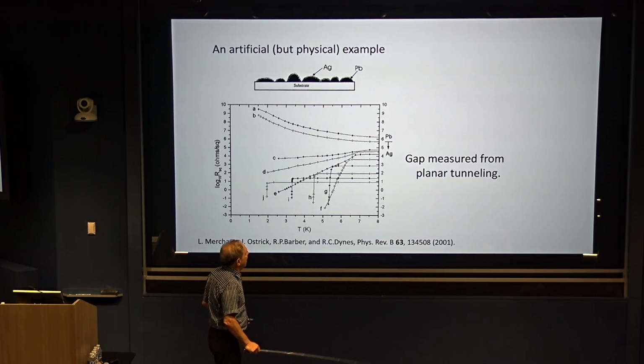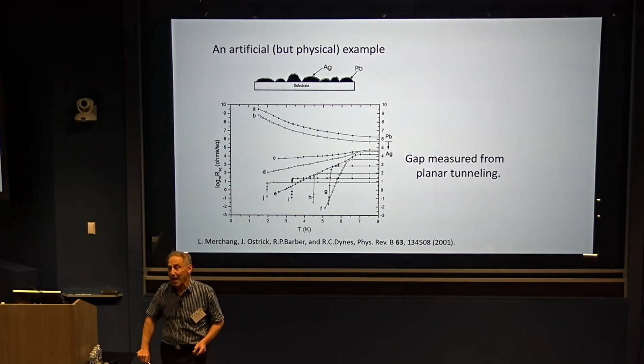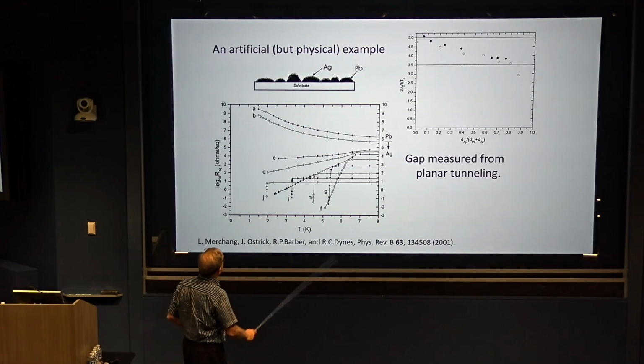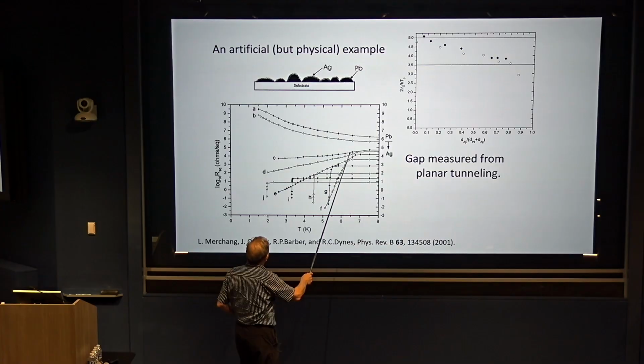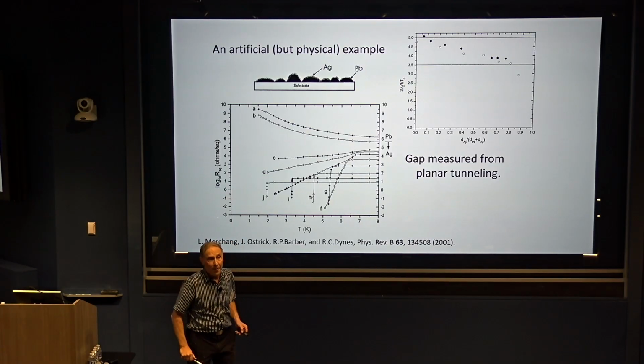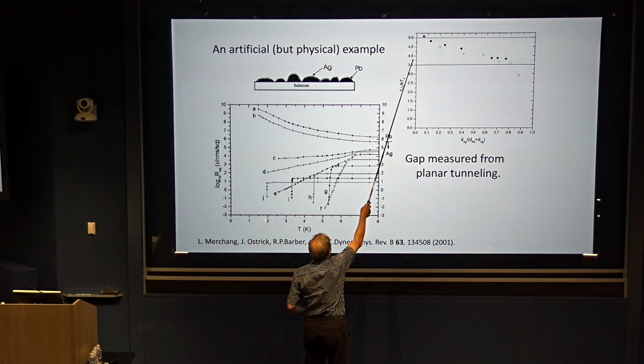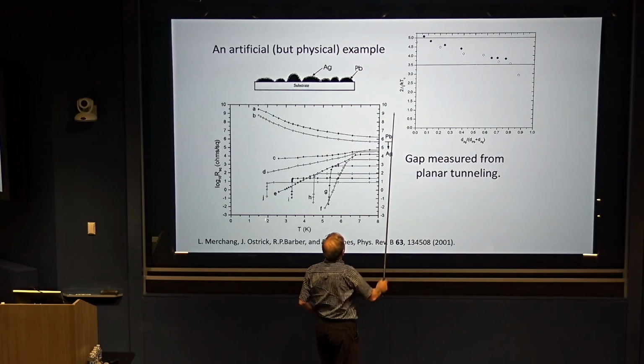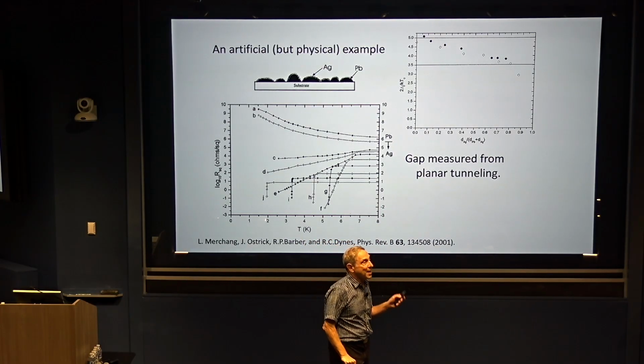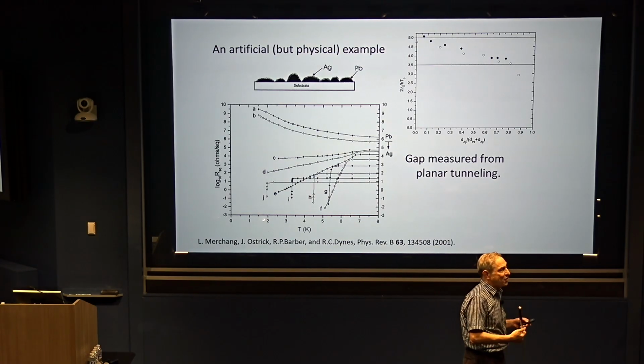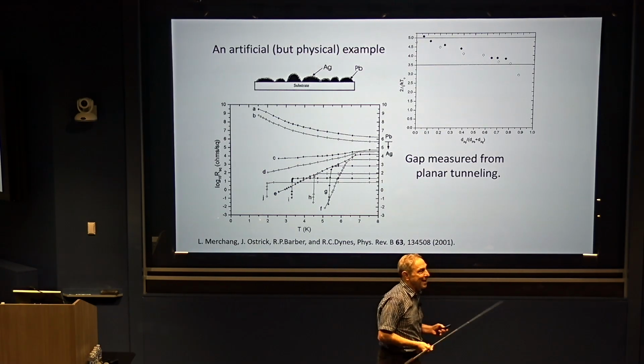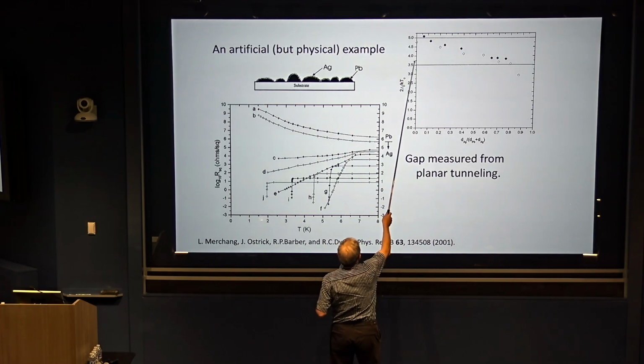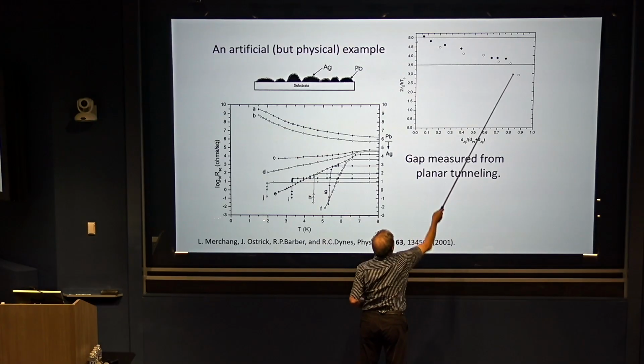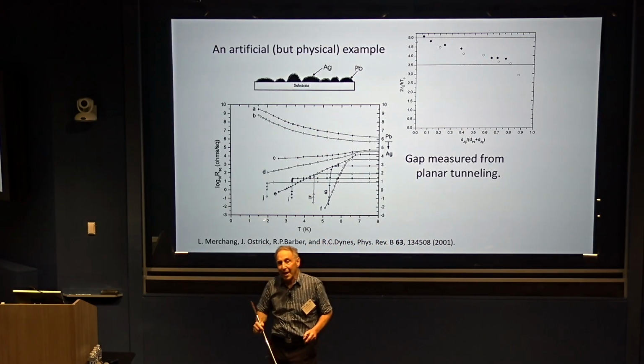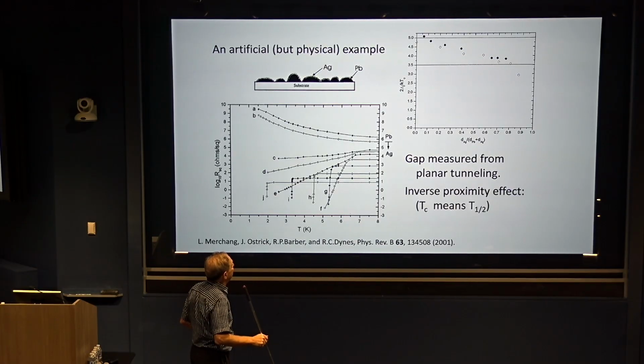What's going on? Also you can measure the gap in these by planar tunneling, and what you see is that the gap as you put on silver first doesn't change and then starts to drop as you put on more and more silver. Just as we would in the cuprates, you can look at 2Δ over Tc. Here, Tc is defined as the temperature at which the resistance has dropped to half of its normal state value. It's not a real Tc. It's some sort of practical metric. But you see that the gap starts big and drops down to a sort of BCS value.